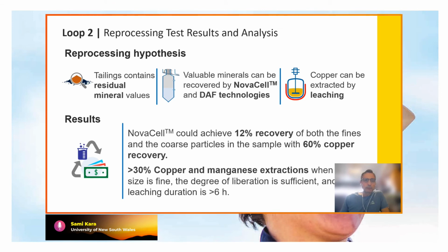For loop 2, reprocessing results suggest that the NOVA cell technology we have used could achieve 12% recovery of both the fine and coarse particles in the sample, with a 60% copper recovery. More than 30% of the copper and manganese extraction is possible when the size is fine, the degree of liberation is sufficient, and the leaching duration is more than 6 hours.